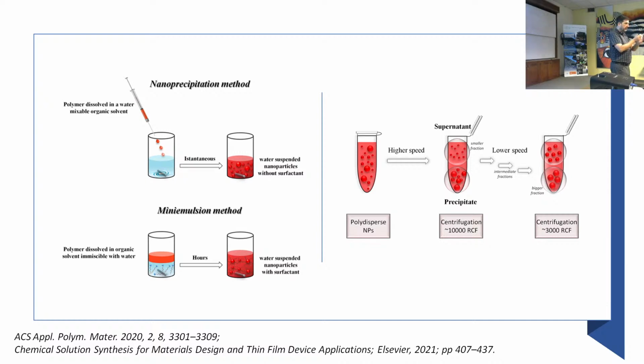And so they will make spheres, and you create the nanoparticles that will be suspended in water. And this is a very straightforward method. Then you have polydispersed nanoparticles, but if you do centrifugation, the bigger particles will deposit in the bottom, the smaller particles will be on the upper part.